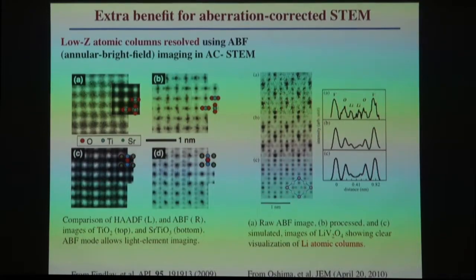Unexpected benefit for aberration-corrected STEM: if you use the so-called annular bright field mode, you're able to actually perceive low Z atomic columns. This was not anticipated way back when people were doing high angle annular dark field, Z contrast imaging. You've probably all heard of Z contrast imaging. It was thought that low Z elements would not be visible in these aberration corrected STEMs, but people said, okay, let's try and do some annular bright field. And here is a case where you have titanium dioxide and the oxygen atom columns are visible. You can see the structural model, oxygen atoms visible.